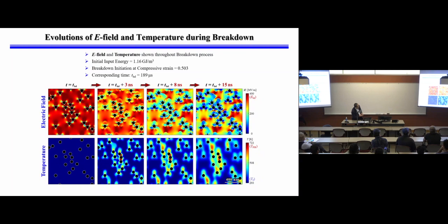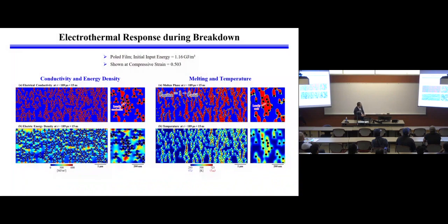So here is what happens. You have to reach a threshold of E field intensity for the breakdown to happen. But once it begins to happen, just 3 nanoseconds, 8 nanoseconds later, you can see that the E field decreases because the electrical energy is converted into heat. You have rapid temperature increase. You have the so-called hotspots that cause the melting. And then, of course, temperature increases and then the initiation of reaction.